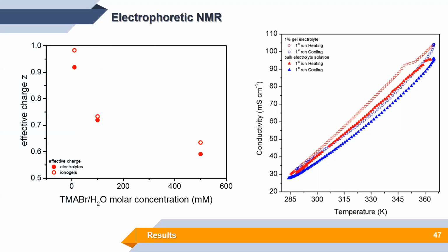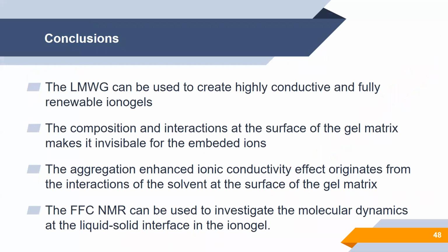And this could also support the information from the field cycling that because of the presence of the gel matrix, which entraps some part of the solvent molecules, the solvation shell can be thinner because fewer molecules of the solvent are available to do this. And because of that, the screening of the electric charge of the ions is less. So the effective charge is higher. And what is more important, we observe the same effect for the anion. So both cations and anions in the same Ionogel have higher effective electric charge.